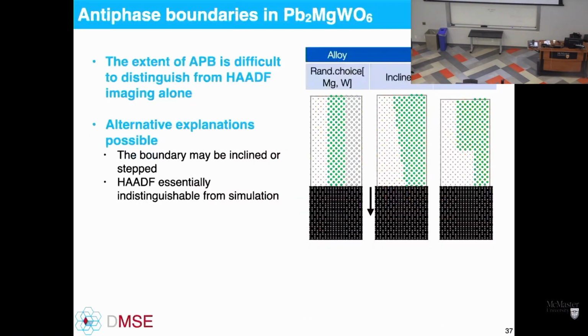The problem with using high angle annular dark field STEM is that you can get many results that are ambiguous and that are not easily distinguished using one image alone, or even defocus series can be very ambiguous as well. But there are alternative explanations for that same contrast. One is that it's just random, so this would be through the thickness of the sample, this direction from top to bottom. The electron beam is along that direction from top to bottom. In this case, a random alloy gives me that middle contrast. An inclined boundary would also give me the same sort of contrast, and a step boundary would also give me that exact same contrast. So which is it?